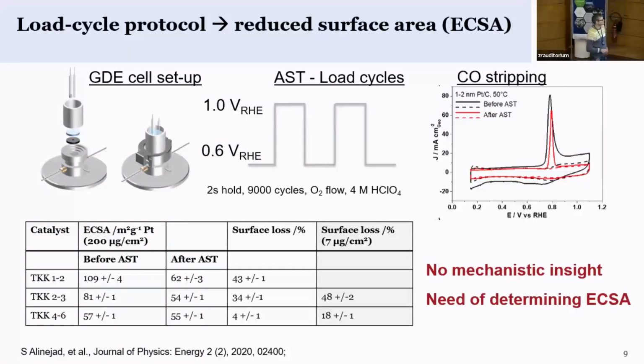And what you see is, of course, that the small particles have a larger area at the beginning, whereas the large particles, as expected, have a lower surface area. You measure the surface area electrochemically by adsorbing, for example, CO, and then oxidizing, and based on the amount of the oxidation charge, you can calculate the areas.